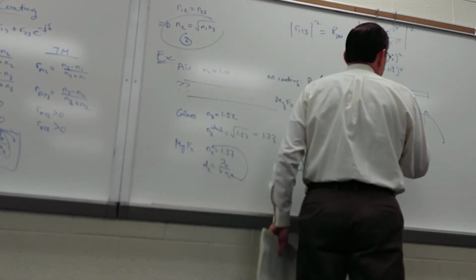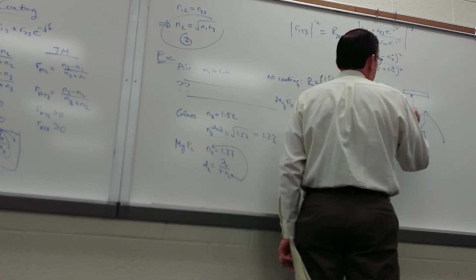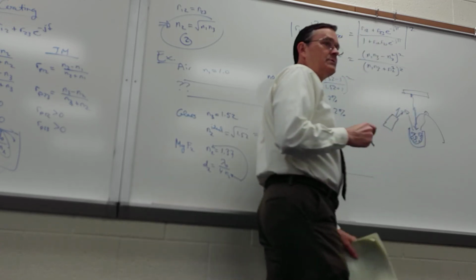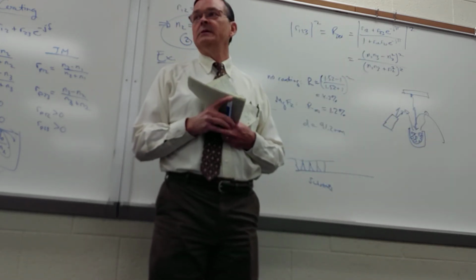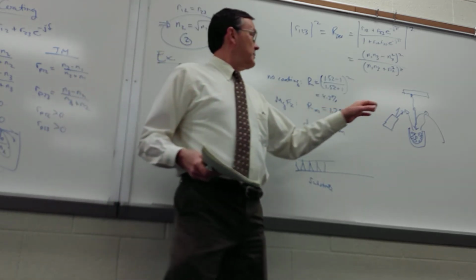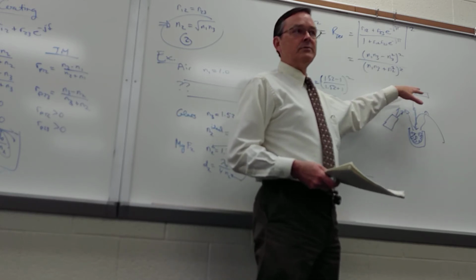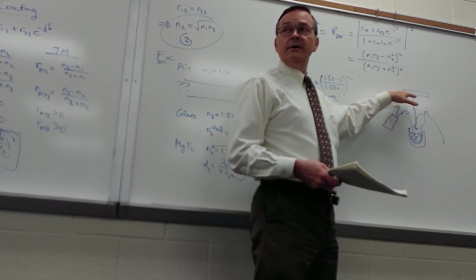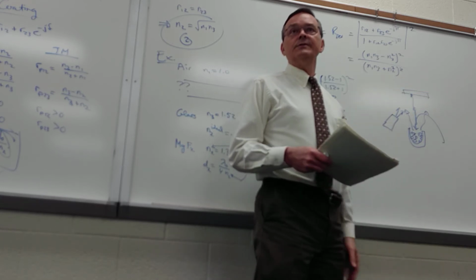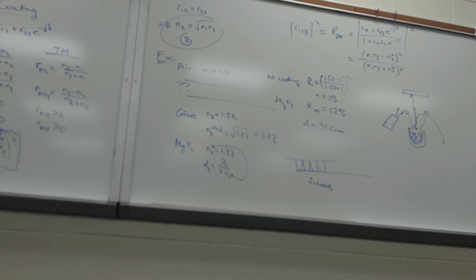Well, there are numerous ways, but one key way is to take an ion gun and basically bombard the surface with, say, argon ions, and then the kinetic energy of the argon ions gets imparted to whatever it is you're trying to deposit. That allows the molecules to have more energy. They move around, they find a better spot, and then get a denser film. So if you ever have to buy an e-beam evaporation system and you care about your film quality, then usually you want to get an ion gun.